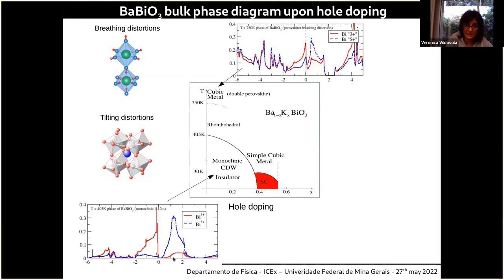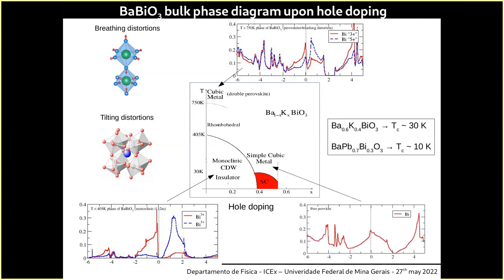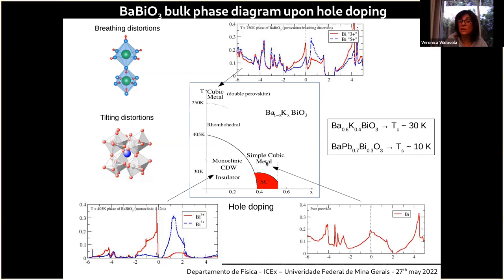And if you see the density of states corresponding to the monoclinic charge ordered phase, here you see the complete disproportionation between the bismuth 3+ and the bismuth 5+. When you dope the system, after a given critical doping, the bismuth turns into a simple cubic metal. Because if you dope it enough, the bismuth is far away from the valence skipper situation, so it doesn't need to double the cell. So after a given doping, the system turns simple cubic metallic, and below a critical temperature, it becomes superconductor.